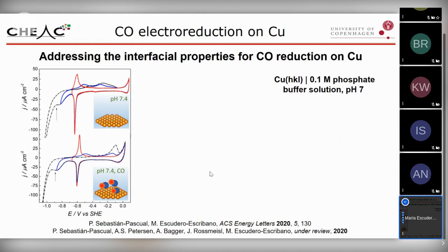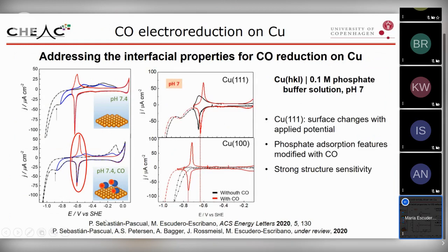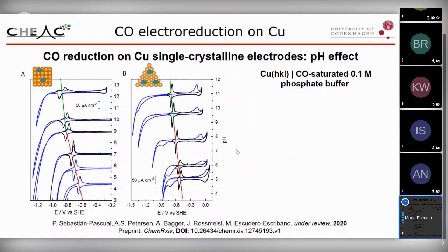This is the same kind of experiment at pH 7, and what we see here, in the presence of CO, is that the characteristic features of the anion adsorption are modified with CO. We also see that the structure is very different, and where CO is adsorbed is very different for copper 111 and copper 100. Having these preliminary results, we were interested in pursuing a more systematic study on both copper 111 and copper 100, and studying this interface over the whole pH range. And this is something that Paula did.